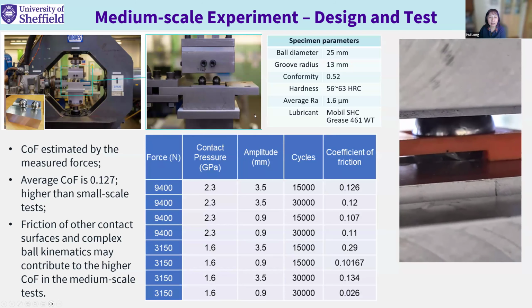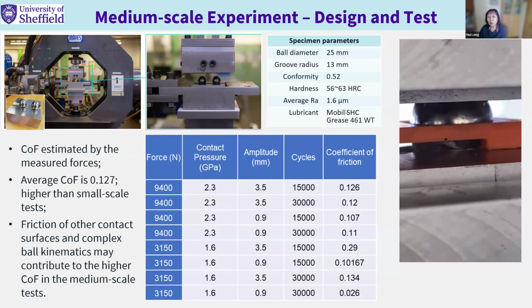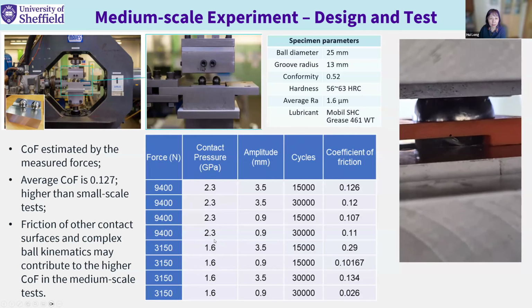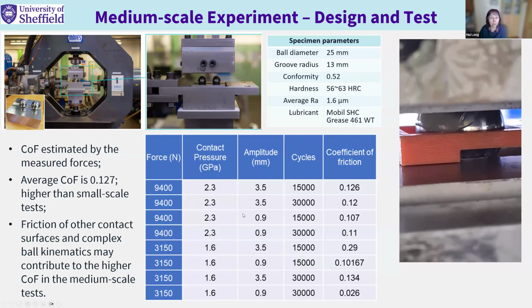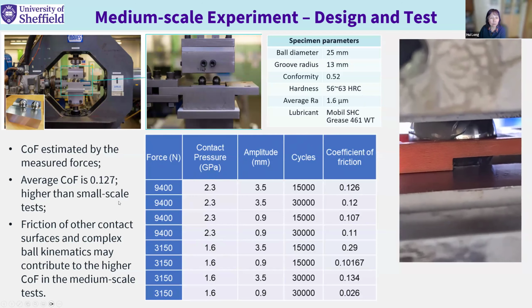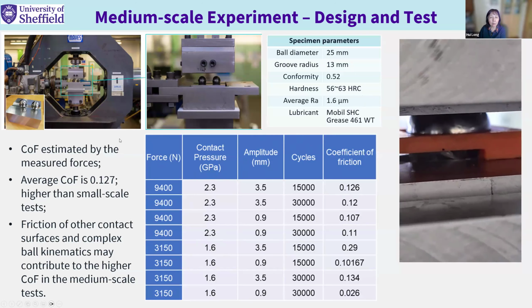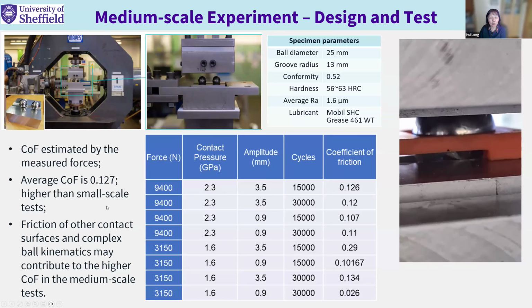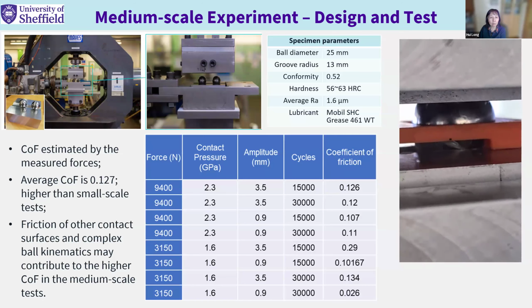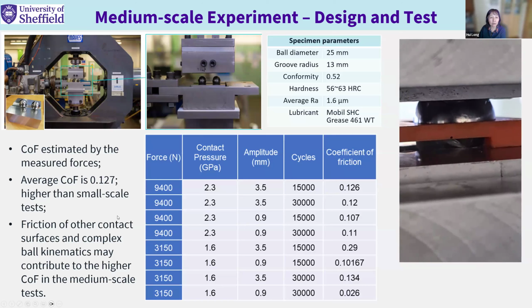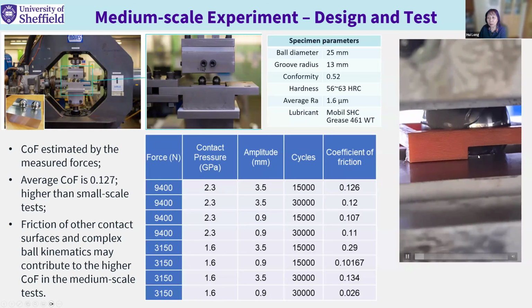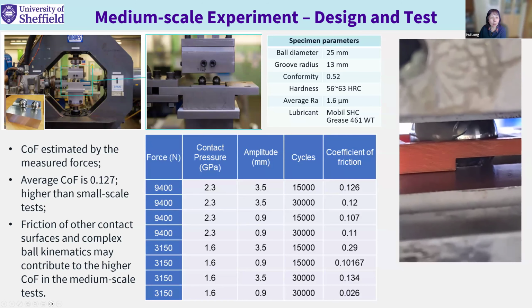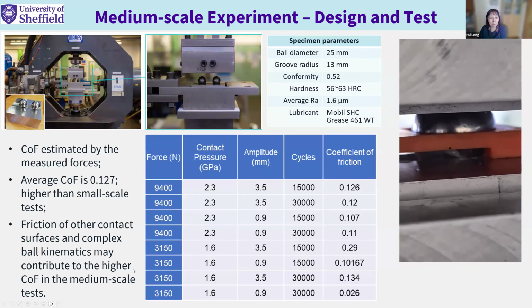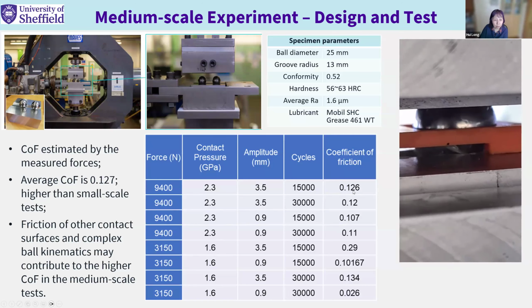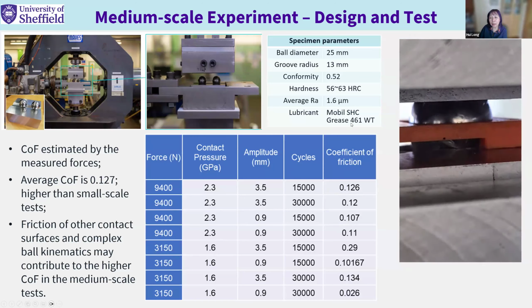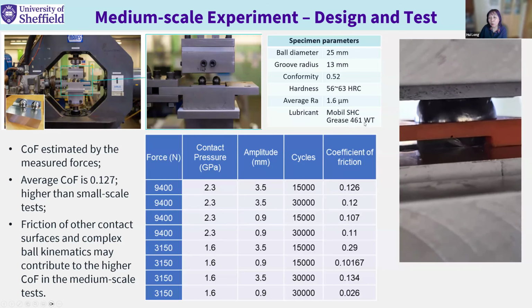Using this rig, we can look at a ball diameter of 25 millimeters. So we developed this test plan. We can determine the average friction coefficient by using the force measured by the rig. As we can see, the friction coefficient is higher than in the small scale test. We believe this is because this rig design involves other contact surfaces and also more complex ball movement, as you can see. This may contribute to the higher coefficient of friction. We use a grease lubricant, commercially available, the only one we found for wind turbine applications.